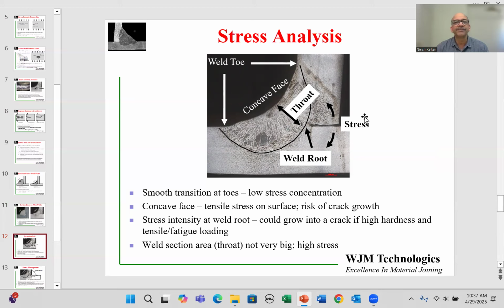So here we are looking again at the toes of the weld. In this particular case, the toes have a nice blending. So there's a smooth transition between the face of the weld and the base metal. So that's a good thing. That reduces the stress at that transition point. We do, however, have a concave face on this one. So we are going to have tensile stresses on the face of the weld. So that is a little bit of a risk.